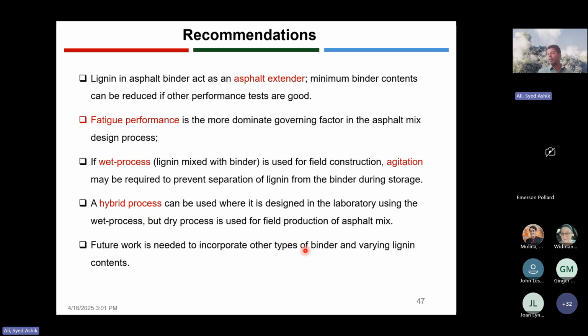So what are our recommendations from this study? We have seen that the lignin is actually acting as an asphalt extender. So minimum binder requirement can be reduced if we use lignin in our asphalt. And also fatigue performance will be the dominant governing factor for asphalt mix design.